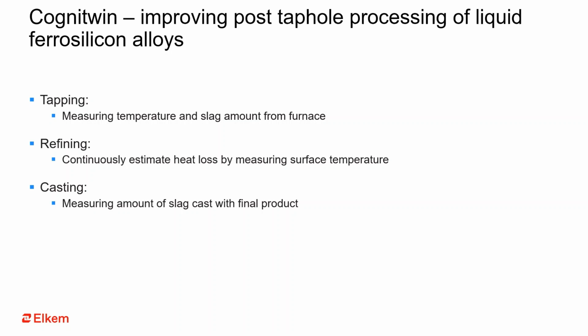The output from infrared cameras combined with image analysis can be summarized as follows. For tapping, a continuous temperature measurement is done together with a quantification of the amount of slag following the metal from the furnace. In the refining alloying stage, the infrared camera gives a continuous temperature measurement as well as slag coverage measurements, both of which are essential to monitor the heat loss during metal processing. In the casting stage, the slag amount during casting can be measured. All of these parameters can now be provided to the online mass energy model that will ensure optimal processing of the liquid ferroalloy, both in terms of maximizing the yield and ensuring proper quality of the finished product.